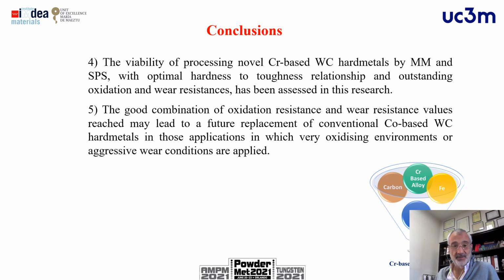So the viability of processing of this novel chromium-based tungsten carbide hard metals by mechanical milling and spark plasma sintering, with optimal hardness and toughness relationship and good oxidation and wear resistance, has been demonstrated with this research work. And this good combination of oxidation resistant and wear resistant values might lead to the future replacement of cobalt-based tungsten carbide hard metals. So those applications are promising, and I think it opens a new way to develop new families of materials, avoiding the use of cobalt.